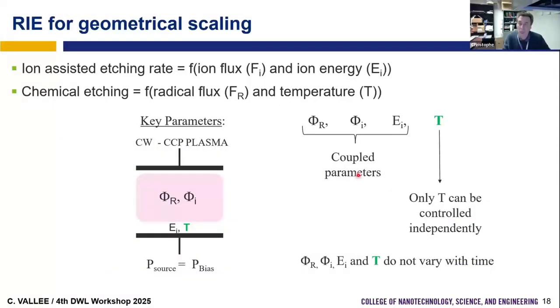To understand why we did this evolution of the design, I just tried to go back to a very simple understanding of a plasma etching process. When we do a plasma etching process, we have the ion-assisted etching. If the process is mainly ion-assisted, the etching rate will be proportional to the ion flux and the ion energy. And we have the chemical etching process, where the spontaneous etching depends on the radical flux and temperature. So these are the two main parameters every time we have chemical etching or ion-assisted etching.